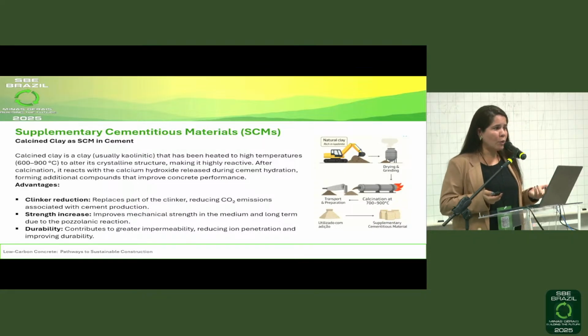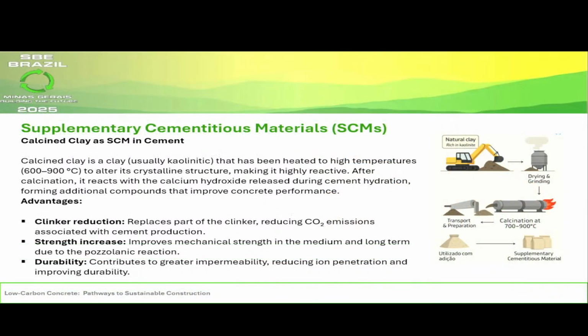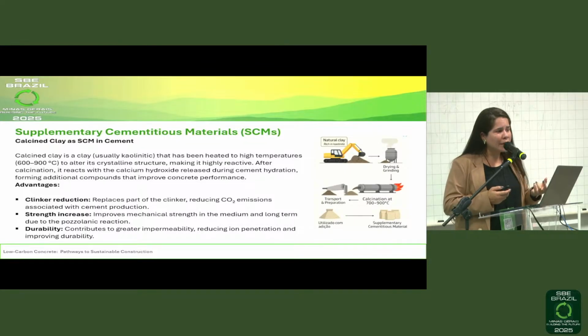So what do we do? We need to look for other materials. We need to look for other supplementary materials. So, for example, calcinated clay. If we find a good source of kaolinitic clay, we can have a good source of this material. We can treat this material and use it with cement because it interacts with calcium hydroxide and it increases resistance and durability of concrete. This is not a material that will enter inert in the composition. It will increase durability and strength.